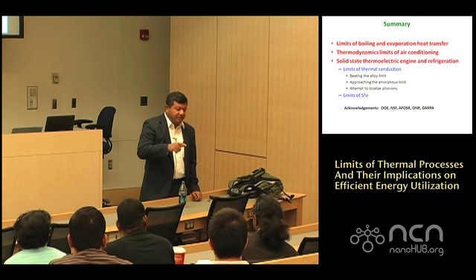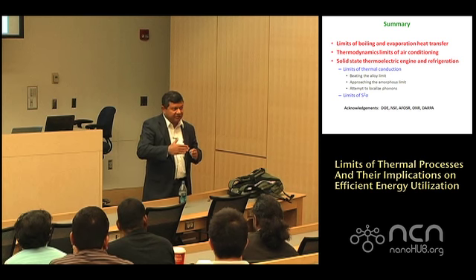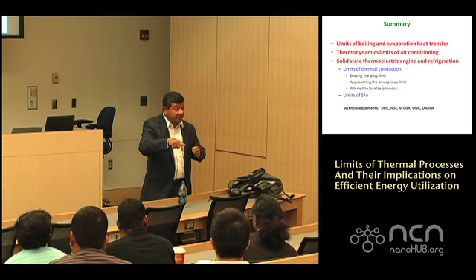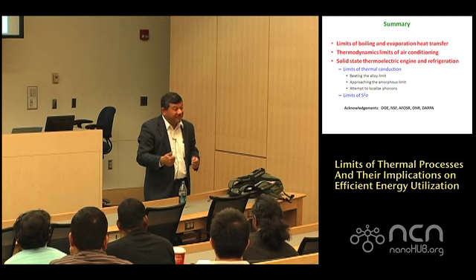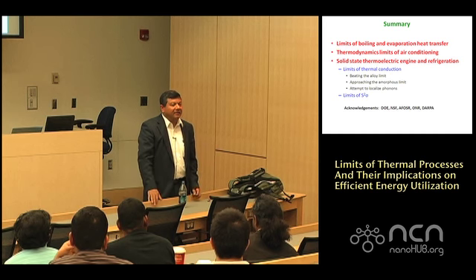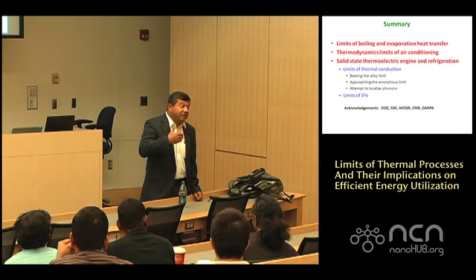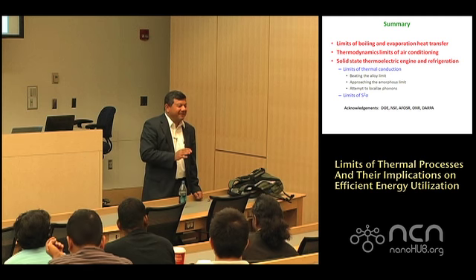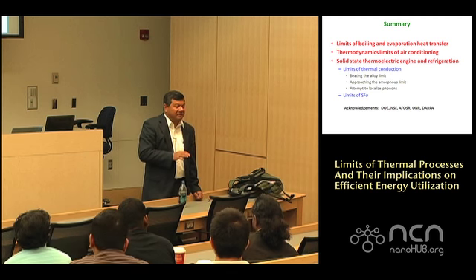But there's also more to it. There's electron momentum conservation. If you have a flat interface, like Snell's law, only a few electrons will go through. Others will be totally internally reflected. So they put some very interesting roughness on this to get other electrons to go through, increasing the transmission, just like in optics. Thereby they have been able to increase the electron conductivity without affecting the thermal power. There's some very nifty bandgap engineering and structural engineering that have gone into these structures on the electronic side.